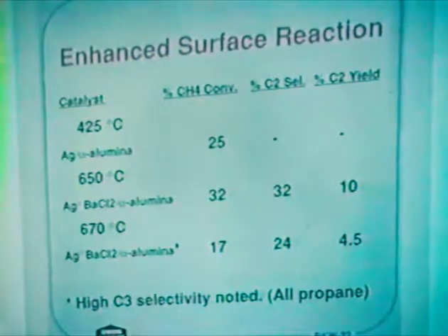And Ken Campbell is studying some other catalysts, a different system, and notice the significance of this. In the methane oxidation reaction, your C3s are largely propylene. It has been shown that this largely occurs through addition of methyl radical to ethylene in the gas phase. If you see no propylene, we do not have the same heterogeneous-homogeneous mechanism as all of the rest of the catalysts.